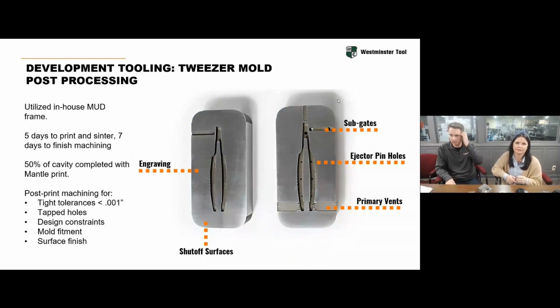So in terms of the details, what did we have to do afterwards? Now I think I've started to build a case of what you can do with Mantle. After we printed it, we had about 7 days to finish machining it. We did not touch the part geometry. So the tweezer geometry itself was not touched. What we did have to do is burn in the subgate. We hole popped our ejector pin holes. We did machine in our primary vents just based on the tolerance of those. We ground the entire perimeter of the block, squared up the block, and then ground the shutoff surface just to make sure we had a really good shutoff. And in this instance, we laser engraved the company websites.